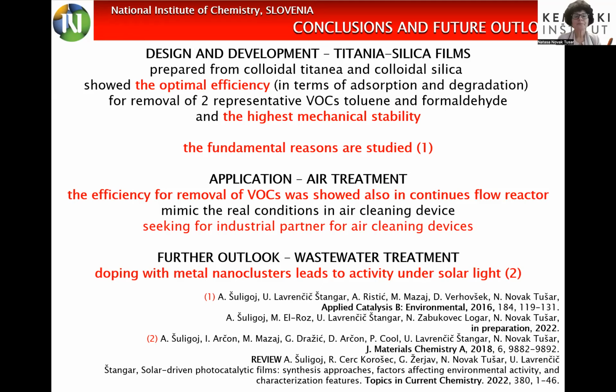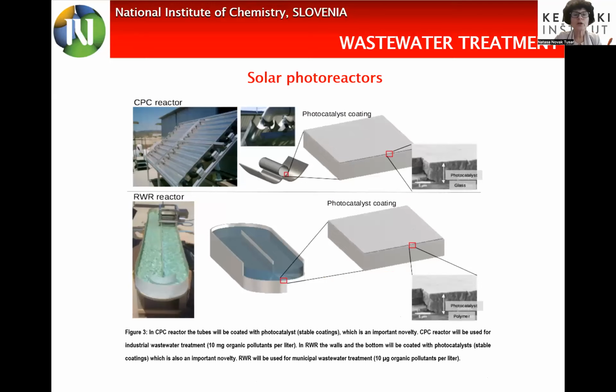So the further outlook is, of course, wastewater treatment, because if we have such mechanically stable coatings, we can dope them with different metal nanoclusters, which make our titanium silica material useful and active also under visible light. So that means that we can use it for solar light wastewater treatment, and that means that we can use it in such solar photoreactors.